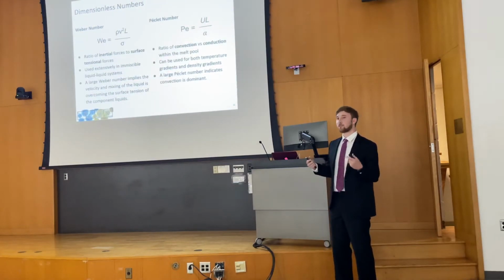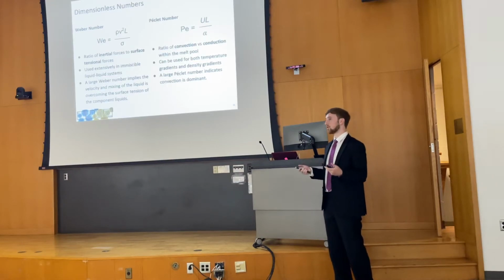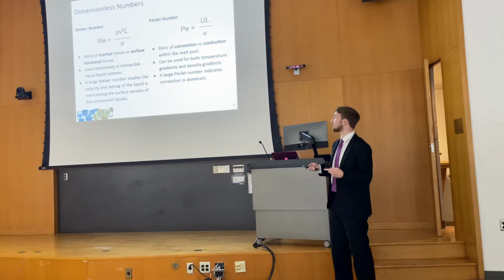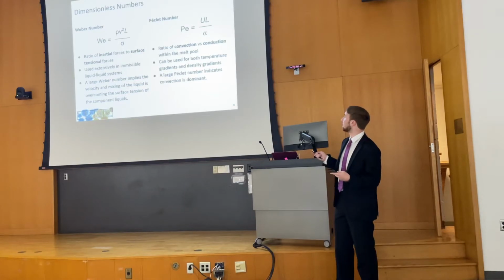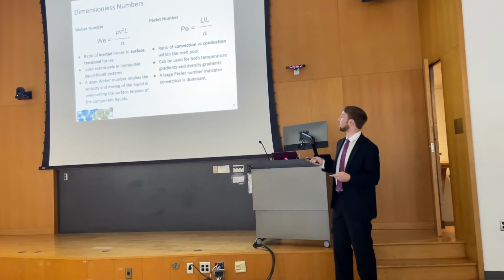We also wanted to quantify what was happening across material systems. So we looked to dimensionless numbers, and because we didn't have temperature data, the two that we settled on were the Weber number and Peclet number. The Weber number is a ratio of inertial forces to surface tensional forces. It's essentially a measure of how much turbulence within the flow and the mixing is overcoming the surface tension of the component liquids.